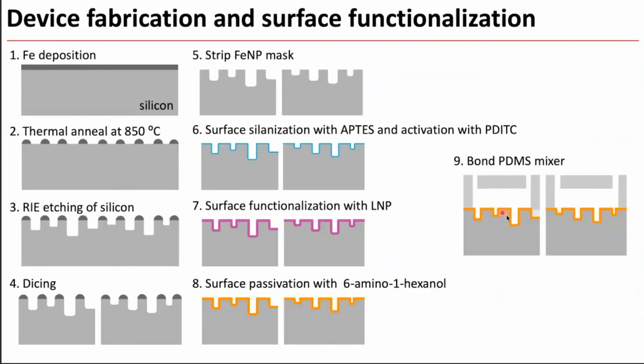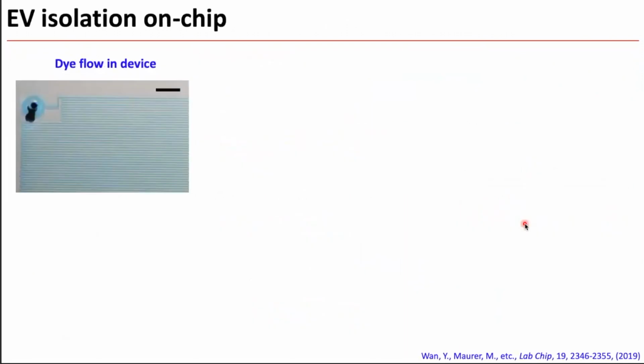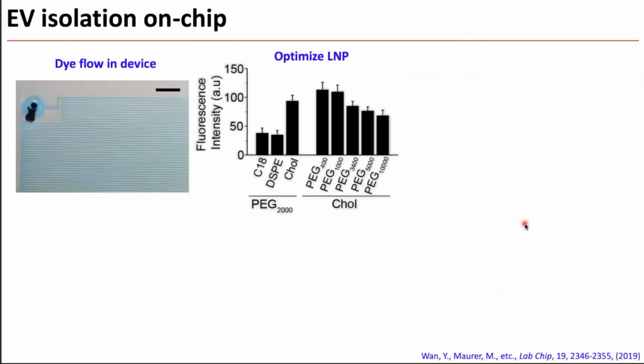So after fabricating the substrate, we also bonded this device with a PDMS micromixer chamber. So this is well known in the microfluidics field. We are using a herringbone structure to mix the sample inside this device so that the sample will be able to come in contact with the surface. So here is the top view of the device.